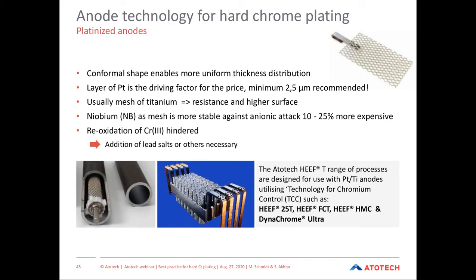It's a titanium mesh with a thin platinum layer. The shape will be constant over the complete lifetime. So there's no changes, no bending, no anything on these kinds of anodes until the platinum layer is worn up. The problem with these kinds of anodes is that the reoxidation of trivalent to hexavalent chrome is not very efficient on the platinum layer. For that reason, Atotech has developed several processes for use with platinized titanium anodes.